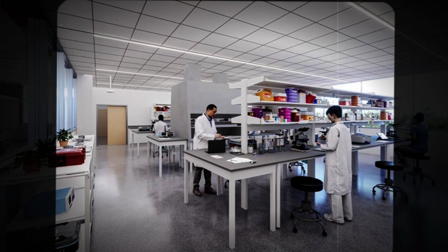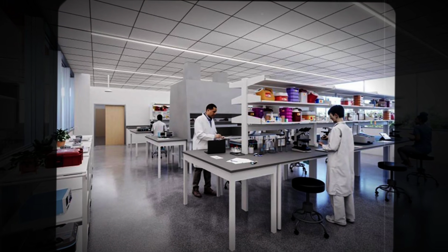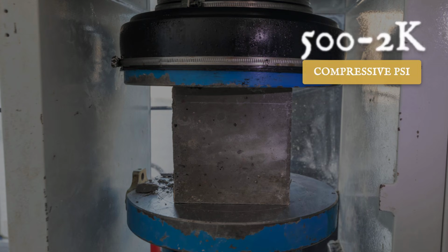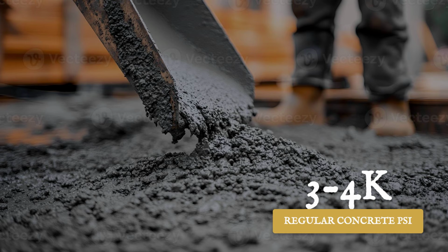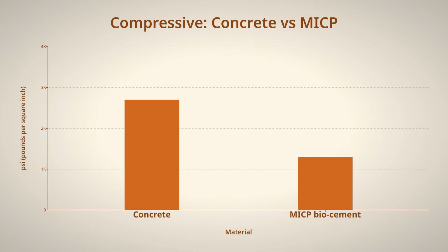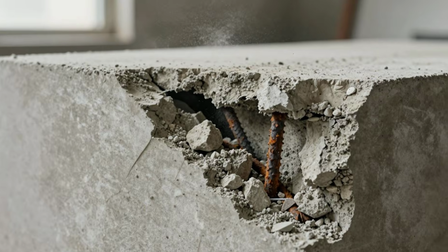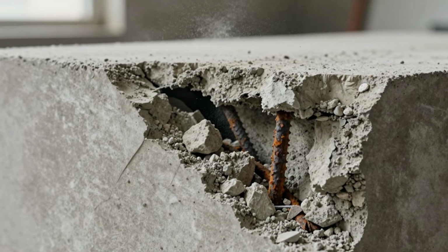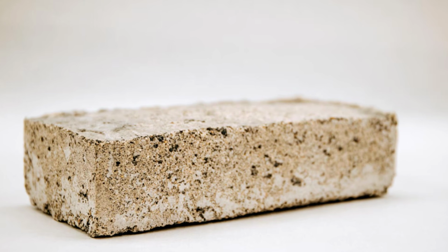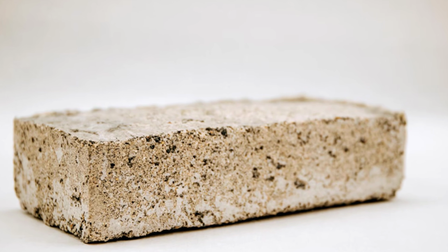The strength of a good MICP block, measured in the UC Davis studies, runs between 500 and 2,000 pounds per square inch of compressive strength depending on how many treatment cycles you put it through. Regular concrete runs 3,000 to 4,000 psi, so it is roughly half as strong as concrete at the high end. But half as strong as concrete, for essentially free, is an extraordinary trade. And here is where the story gets a little darker before it gets better.